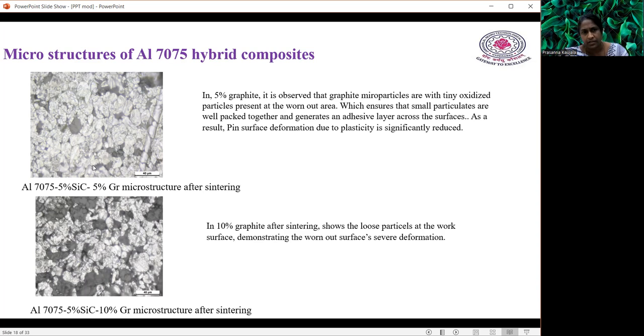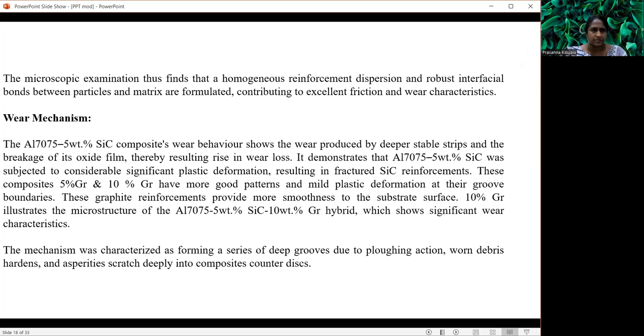It reduces drastically. Whereas the 10% graphite microstructure after sintering shows loose particles at the work surface, demonstrating the worn out surface with severe deformation. So wherever the worn out surface takes place, the deformation is severe. You can see the difference in the microstructure when 5% graphite and 10% graphite are added.